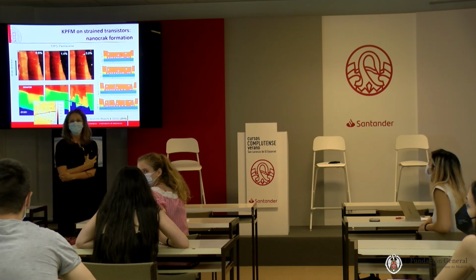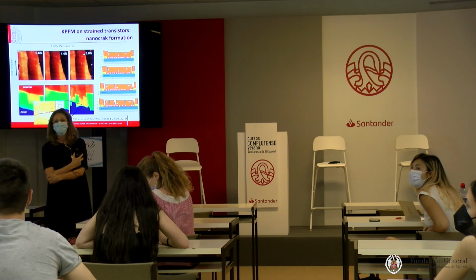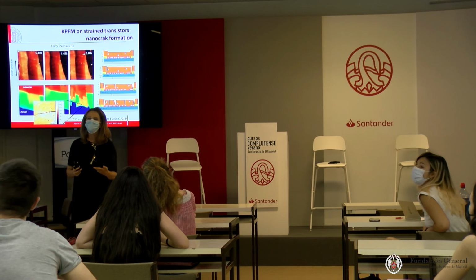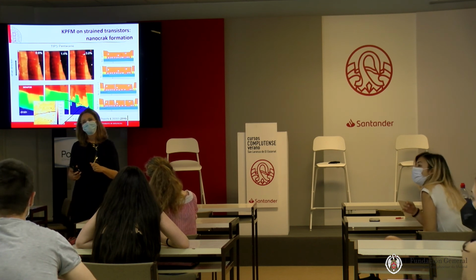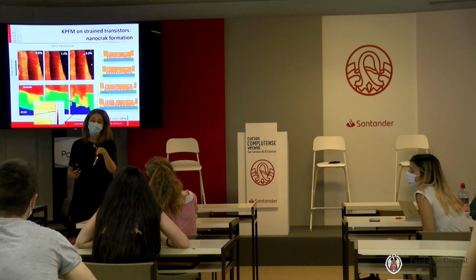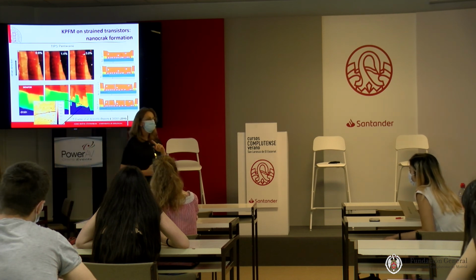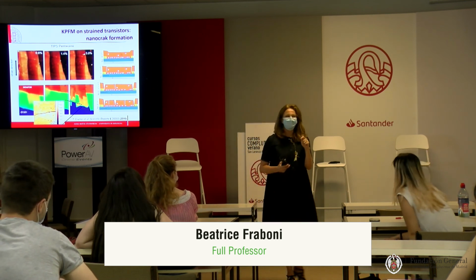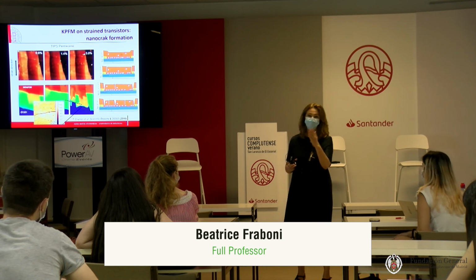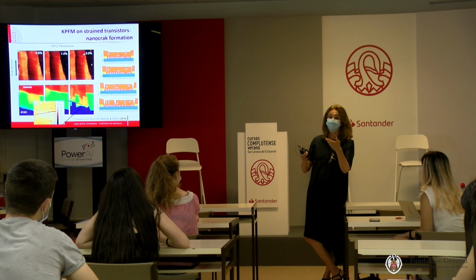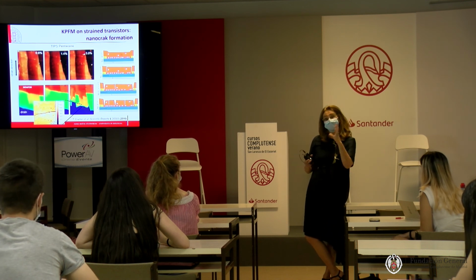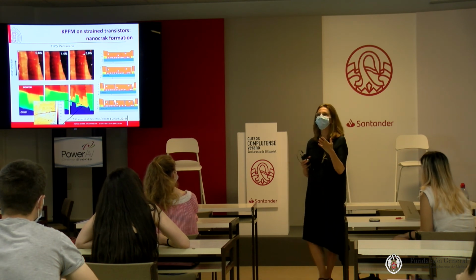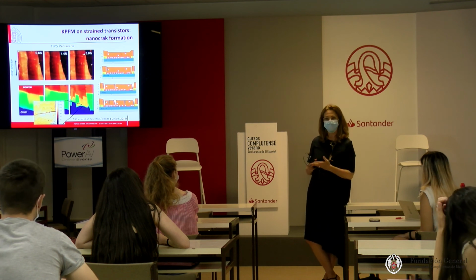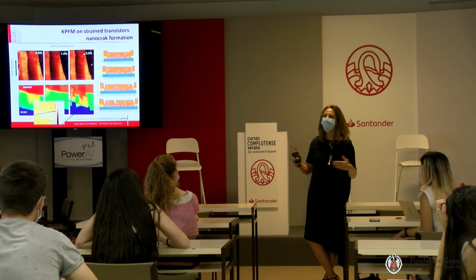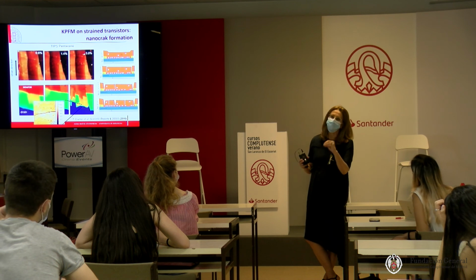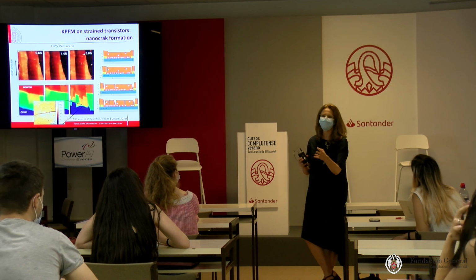Being an organic semiconductor, what might be the problems related to rising temperatures? During operation or during fabrication? Both. I mean the limits due to temperature. Yes. Organic semiconductors are not happy at high temperature. So as always, there is the good side and the bad side. The good side is that you can deposit them at room temperature, and so you can use substrates that do not tolerate high temperature. But the bad side is that you cannot put them at high temperature. High temperature, for example, is above 100, 150 degrees centigrade. So it is a temperature which is very good for normal operation in our life. But if you have to operate them in a furnace, forget it. They will melt. So there is a high temperature limit.